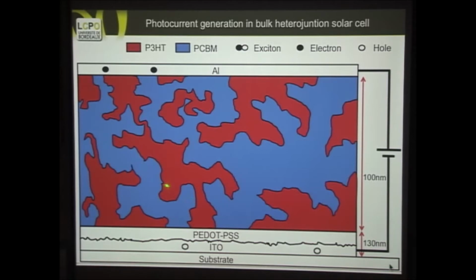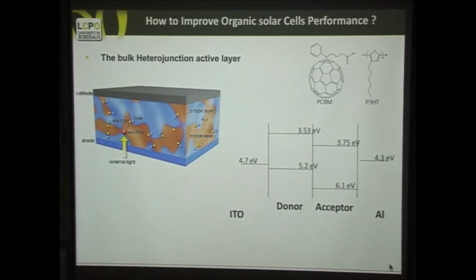So you saw the challenge. You have to make a polymer material that has bicontinuity and not cul-de-sac. You have to make these distances comparable to the diffusion length of these excitons, which is about 10 nanometers. How do you do that? Well, you have to do certain other things. You have to adjust also the energies of these materials, so that means the conjugation length. So when a photon comes in, it can move an electron from the ground state to the excited state. And then you have to have the next polymer, this we call donor, this we call acceptor, that separate the charges. And then we have to remove them. We have to adjust the interfaces here and the energy levels and so on and so forth.